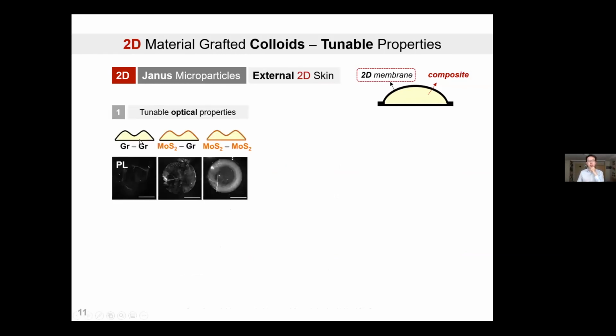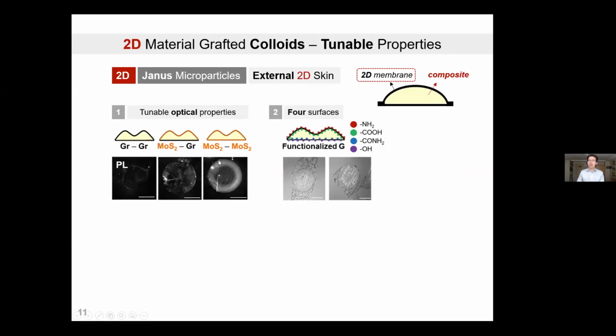You can, for example, control the optical property of the particle by mixing and matching different optically responsive 2D materials. In this case, we're making either a graphene particle, a MoS2 particle, or a hybrid Janus particle with one layer of MoS2 on top and one layer of graphene on the bottom. It, of course, will have different photoluminescence and other optical properties. The even more fun part is that, chemically, with two layers of defined 2D material on top and bottom, you actually have chemical access to four surfaces, because each layer of 2D material has its internal phase and external phase, right?